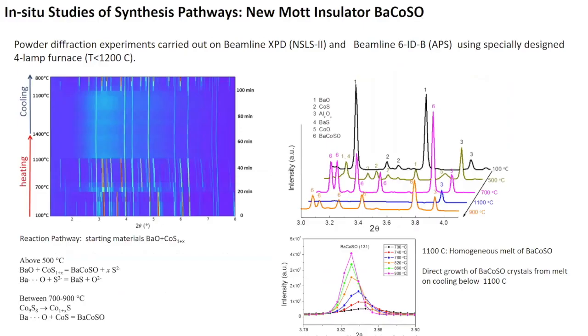So with that, I just want to line things up for the next speaker to tell you about a separate project that we did. And so you might have construed from the cuprate work that sulfur and oxygen should never be found together, but we were not discouraged by that. Instead, we decided to look at cobalt-bearing compounds to see if we could find some new superconductors there. And one of the compounds that we looked at is this barium cobalt sulfur oxygen compound. And in fact, it does turn out that this material is stable and can form from a melt. And we presume we could grow large crystals from a flux if needed.